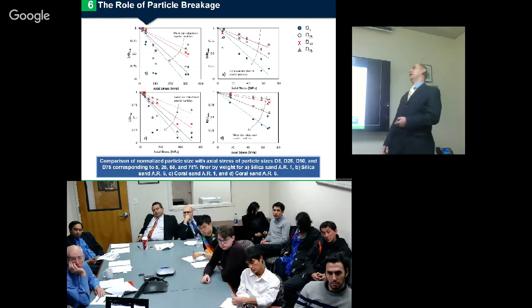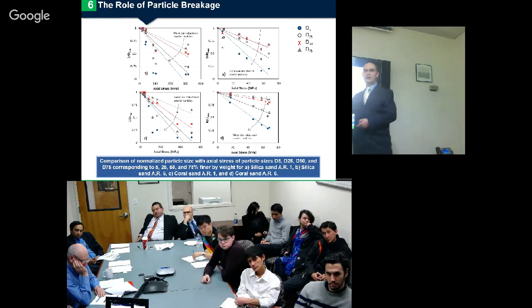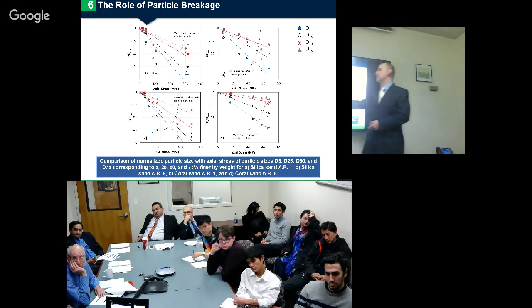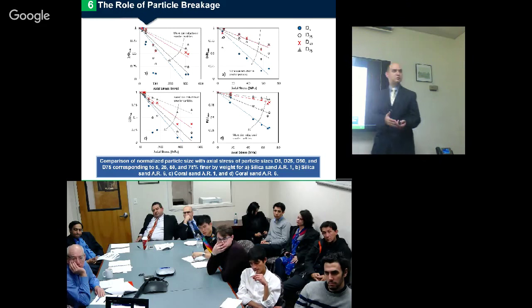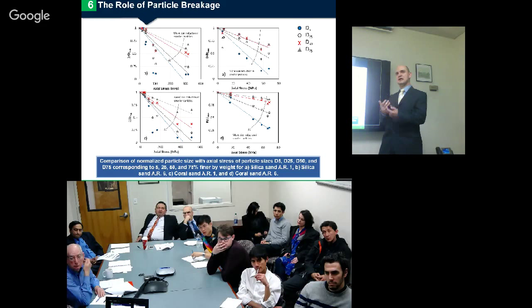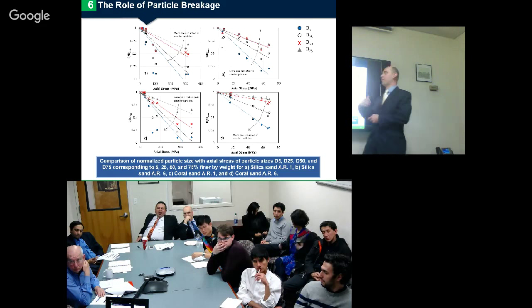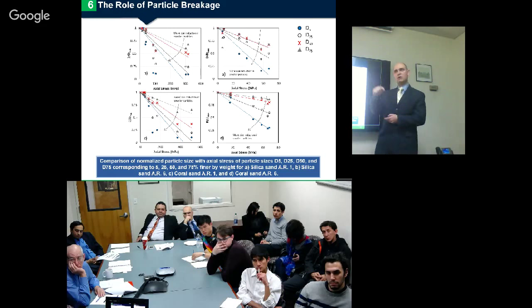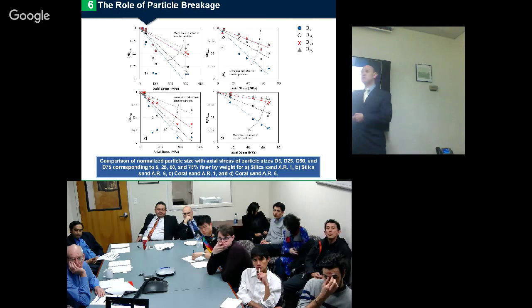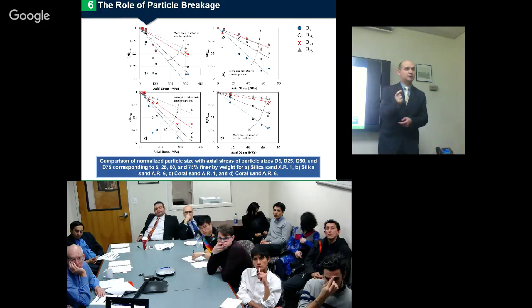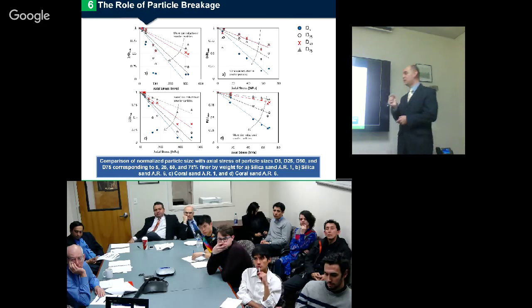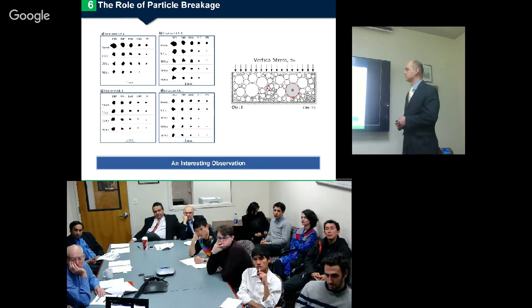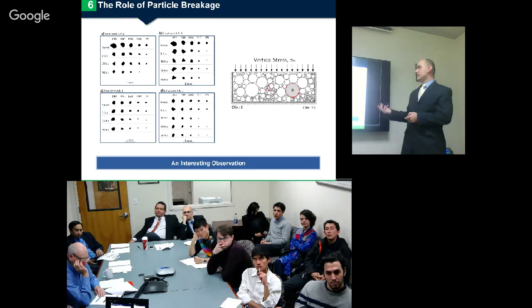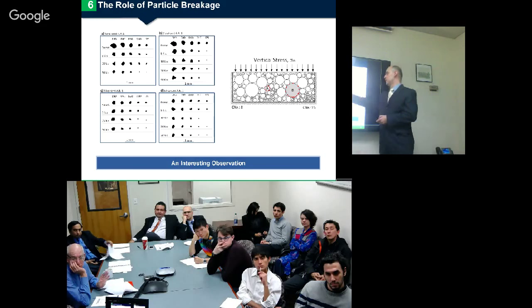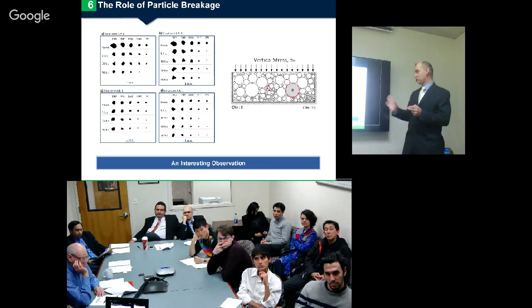And the same with this normalized diameter by taking the actual stress. We wanted to do this in order to see if there is a distinction between plotting the data versus strain or stress, but we saw something similar. The smaller-diameter particle breaks more than the large one. An interesting observation.